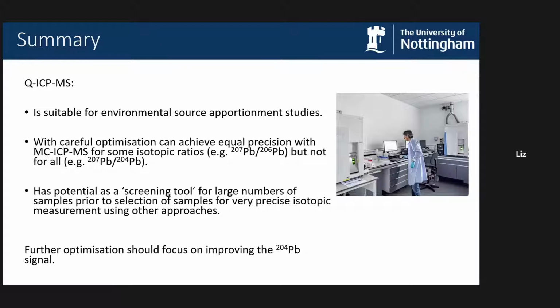Given that it's relatively less expensive and has higher throughput, at about 16 minutes per sample using this technique, it is now possible to screen large numbers of samples first to get isotopic ratios, and then select, with the knowledge of those isotopic ratios, the fewer samples that you actually want to do more precise isotopic measurements on using other approaches. And if we're going to improve quadrupole ICP-MS further, then we need to look at improving the lead 204 signal.